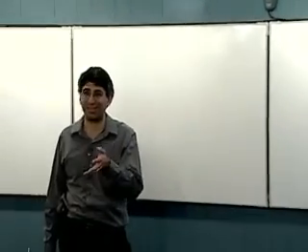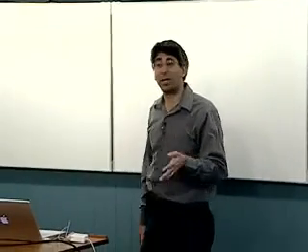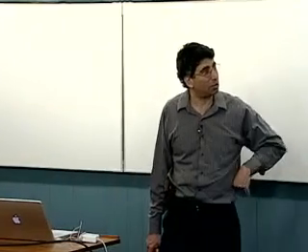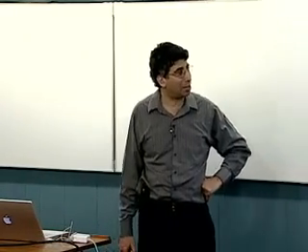I will tell you, we look for spectroscopic changes. Now, this is a non-trivial experiment because, remember, it's 1,000 angstroms of ill-defined material sitting on a nickel electrode, so it's a diffuse reflectance experiment. And we could not detect a spectroscopic shift, but we also concluded that the shift in 10dq would be sufficiently small, probably, that it would be really hard to pick up, and it was poor spectroscopy that we could do. And so we weren't too upset by the fact that we couldn't see that.